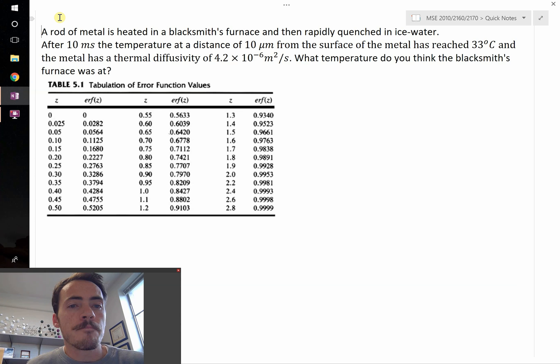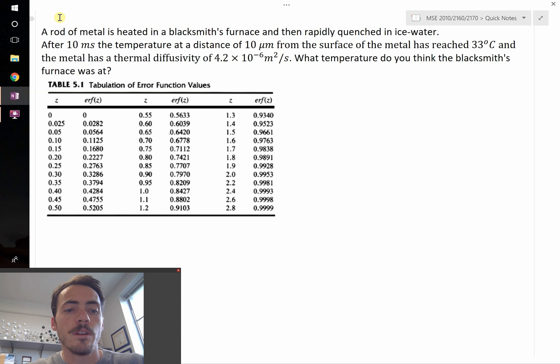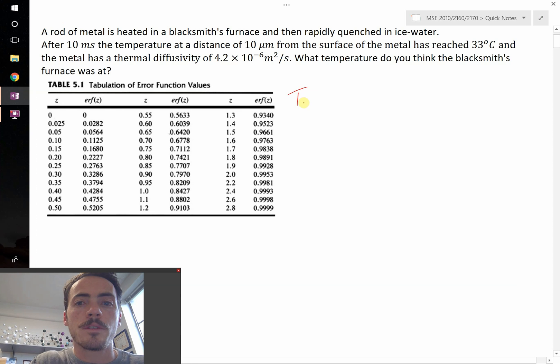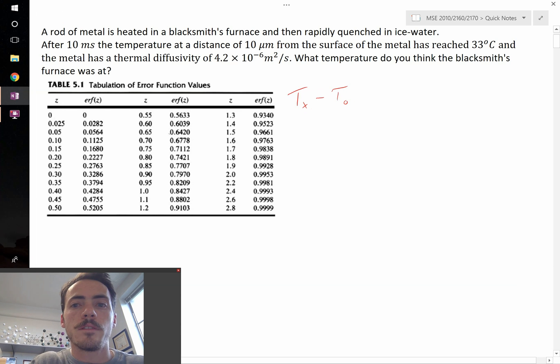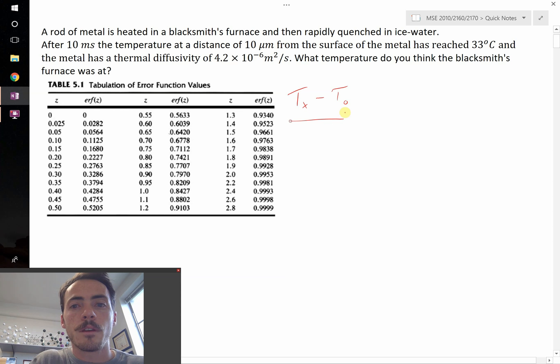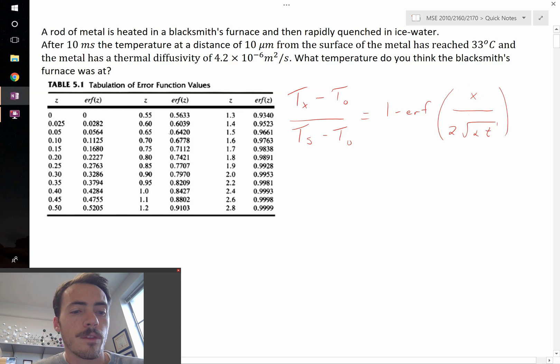This is an example of non-steady state thermal diffusion — the conditions are changing with respect to time. We're going to use the semi-infinite solution to the diffusion equation: the temperature at position X minus the bulk temperature T0, divided by the surface temperature TS minus T0, equals 1 minus the error function of X divided by 2 times the square root of alpha times T, where alpha is the thermal diffusivity of the metal.